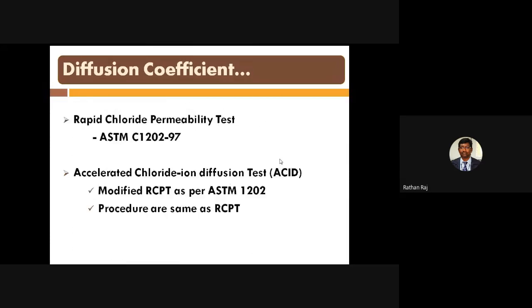For finding the diffusion coefficient, there are two methods being used nowadays. A very common method is the rapid chloride penetration test, which is based on American Standard Testing Method ASTM C1202. Nowadays in the literature you can see another method, called the accelerated chloride ion diffusion test, simply called ACID. This is nothing but a modified RCPT, the rapid chloride permeability test, also conforming to ASTM C1202. There is no separate code available, and the procedures are the same as those used for the rapid chloride permeability test.